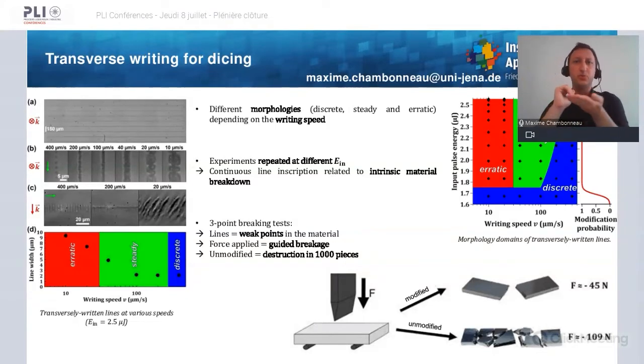Okay, so this was for single pulse and single site. What now if we move the sample perpendicularly to the input laser beam? Well, in this case, we have seen that it was possible basically to inscribe some continuous or discrete lines, but in the bulk of the material. And the line morphology was discrete, steady, or erratic. So discrete here for high speeds, steady for intermediate speeds, and erratic for low speeds.